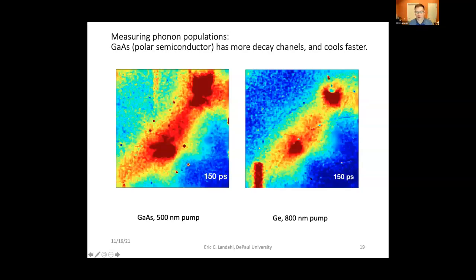And just another couple points about the data. We see that gallium arsenide, being a polar semiconductor, has more decay channels, and indeed it cools faster. We see that at the same time, with comparable overall effects, gallium arsenide really lights up entirely, say 150 picoseconds out, across the entire zone line of symmetry, whereas in germanium there are still distinct hotspots. The zone centers are not connected yet. Phonons are not filled in all of those states. There are fewer channels in germanium, and it indeed cools much slower.